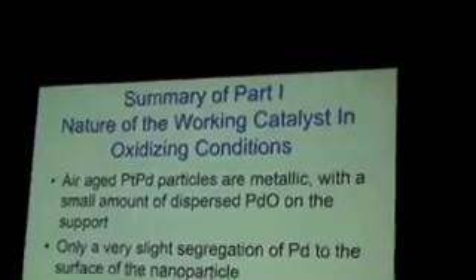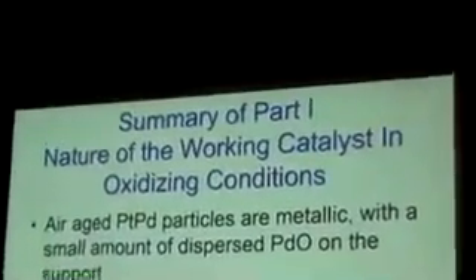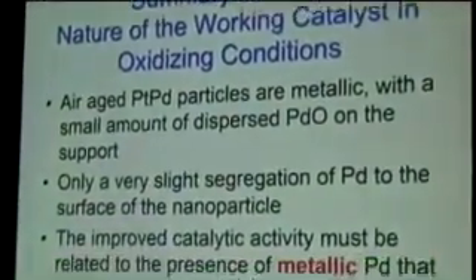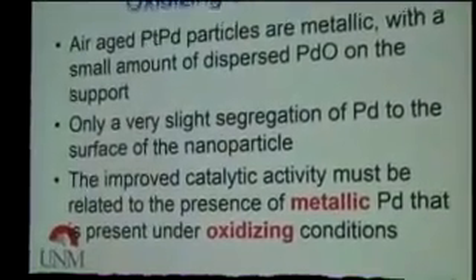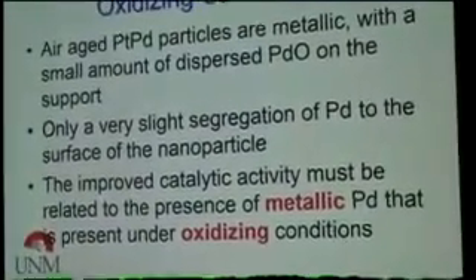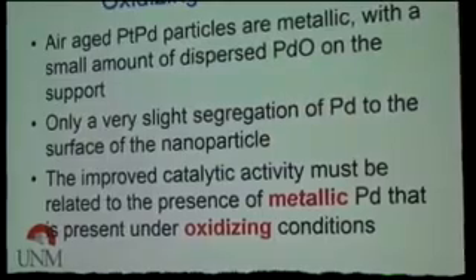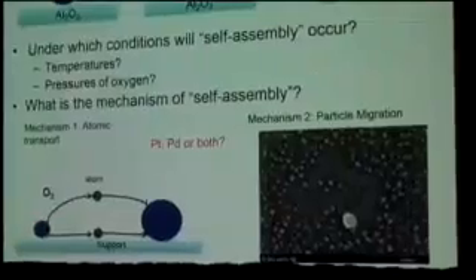Alright? So segregation of palladium to the surface is negligible, and so the key message at the end of the day is platinum keeps palladium metallic under these conditions.